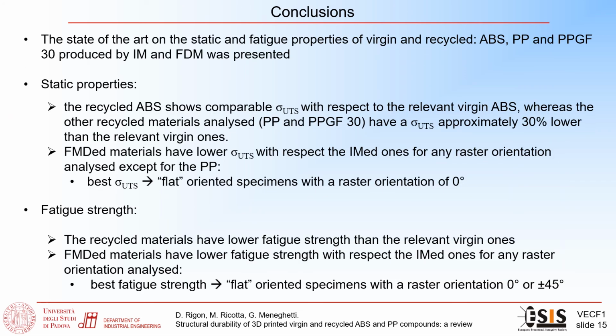At the end, we can draw the following conclusions. The state of the art of the static and fatigue properties of virgin and recycled material produced by injection molding and FDM was presented. Regarding the static properties, the recycled ABS showed comparable UTS with respect to the relevant virgin ABS, whereas the other recycled materials analyzed showed UTS approximately 30% lower than the relevant virgin ones. The FDM materials showed lower UTS with respect to the injection molded ones, over which the best UTS was obtained for flat-oriented specimens with a raster orientation of 0 degrees.